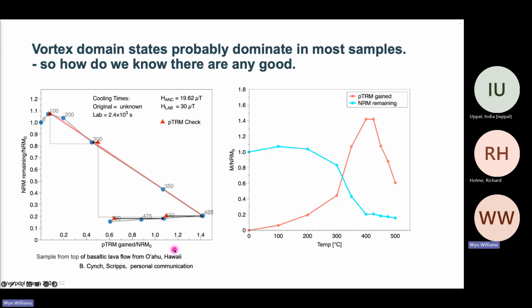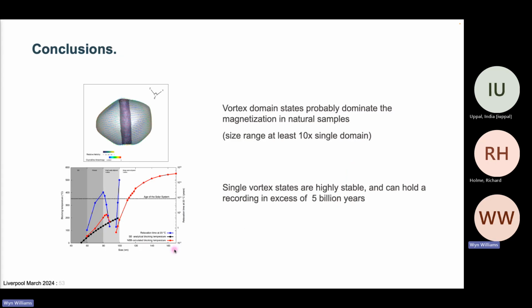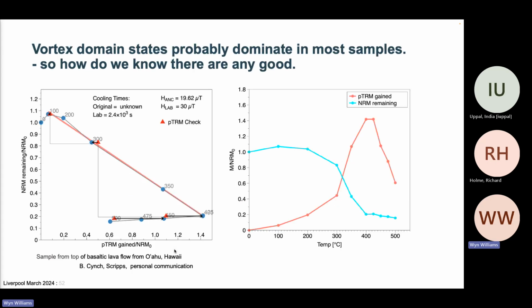The issues that we see in these plots are, in fact, associated with cooling rates, because we are placing magnetization in a different cooling rate than the original one, which shifts the population of domain states from one type of domain to another. If you do it in the same fields, in the same cooling rates, then it's not so bad. This one is in the same cooling rate as the NRM, roughly the same as the lab field, and we get a region at least where the magnetization behaves reasonably well.